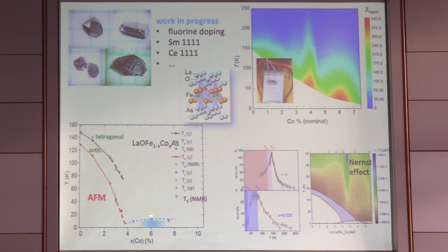So we have an underdoped non-magnetic phase where we have a lot of nematic fluctuations. We have evidence that these nematic fluctuations couple to both the magnetism and the superconductivity. And I've shown the first data on the Nernst effect and Seebeck effect, showing that all transport properties react to strain in these systems, and that maybe the Nernst effect is really special because it could be a probe for nematicity even without straining.